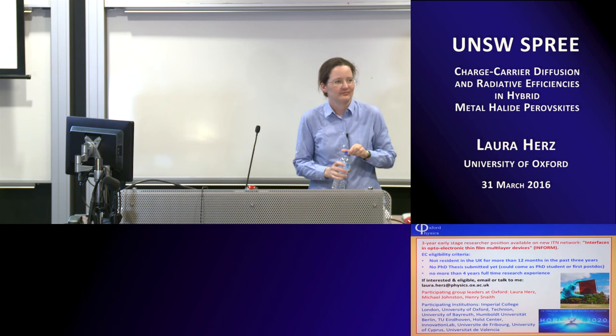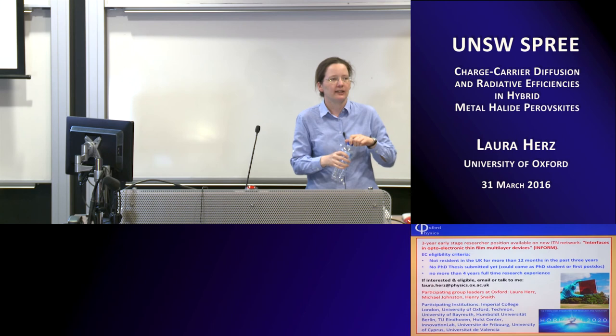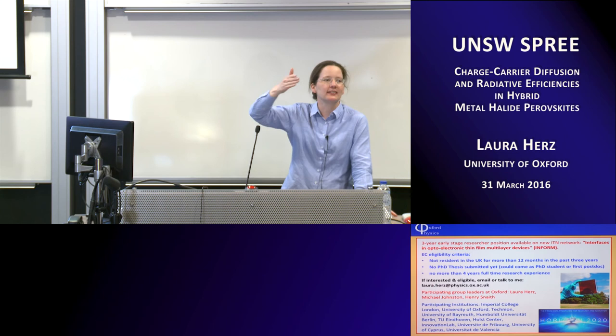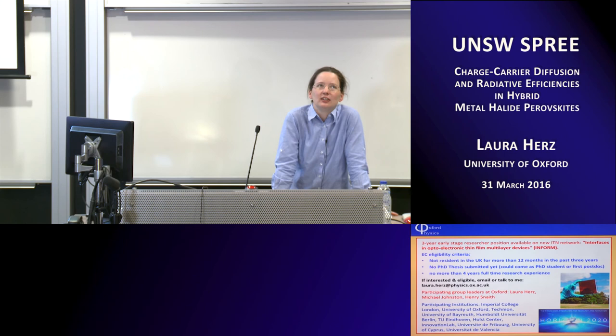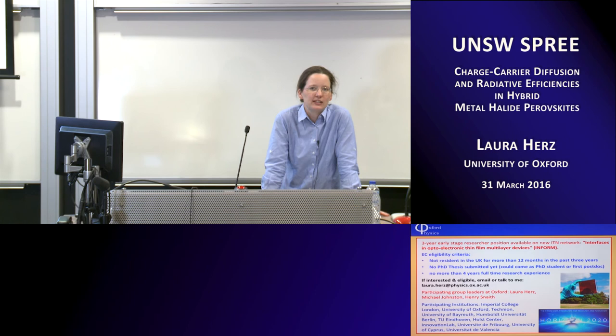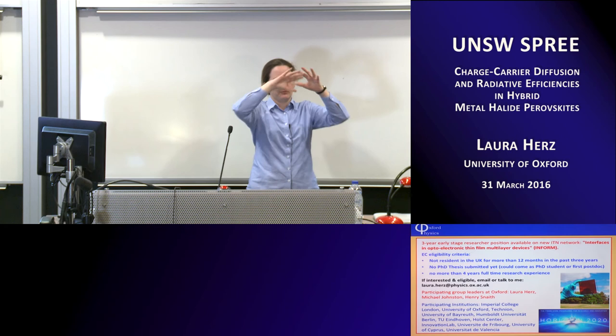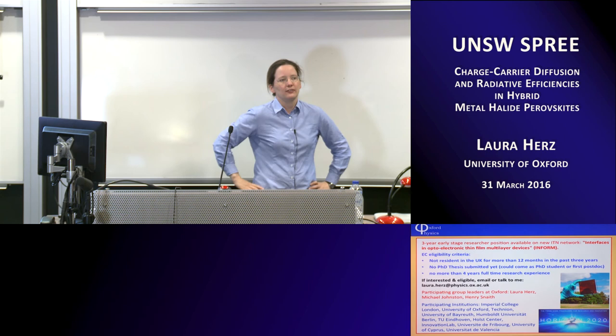One simple question. Have you seen any phonon-related PL emission? In the methylammonium lead triiodide systems, the emission is very broadened and this appears to be mostly due to carrier-phonon scattering. To see actual phonon replicas — we thought we saw something at some stage, but I think maybe it was a surface state. Because the electron-phonon coupling is quite strong, and the system is so broad — the emission full-width half-maximum is about 20 meV at 8 Kelvin, and the relevant phonon energies are around 11 meV — there's still too much disorder broadening at low temperature to really separate that out. So we haven't seen any pronounced replicas yet.